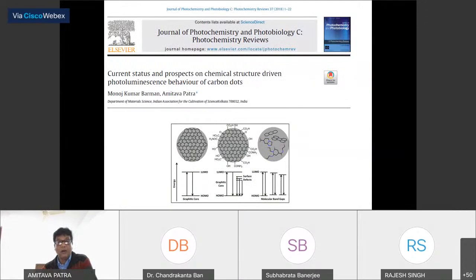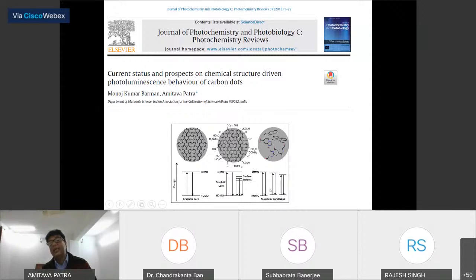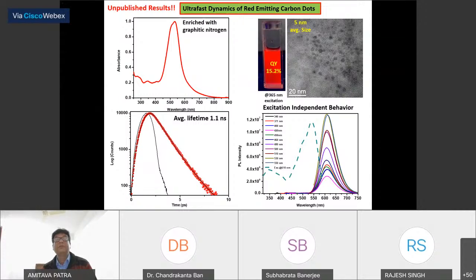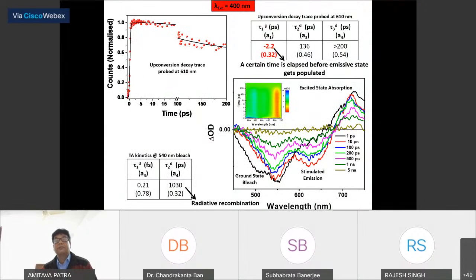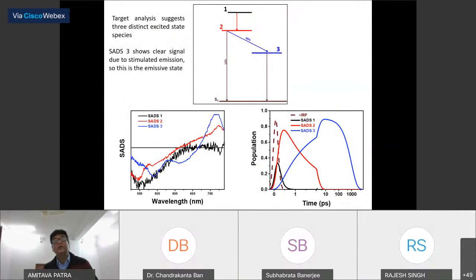And again, in another review article on carbon dots, we try to emphasize what kind of structure matters. If it is a pyrene-like graphitic structure, then there is no defect structure. But if you don't have a graphitic structure and a lot of functional groups are there, then there are a lot of surface defects. So a fundamental understanding of the relaxation process is important to understand why this emission comes. We are also studying the relaxation process of the carbon dot in depth using ultrafast spectroscopy. I will not go into the detail. This is the model we developed using target analysis, showing the relaxation process and whether they have a triplet state or not. In most cases there is no triplet state, but they have different levels of states, so they can control the relaxation process.